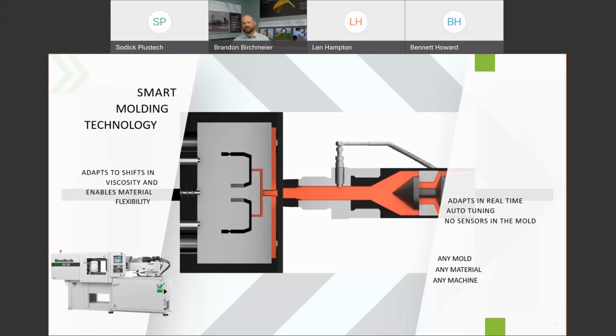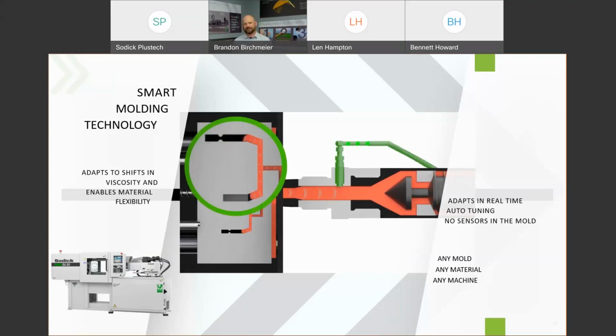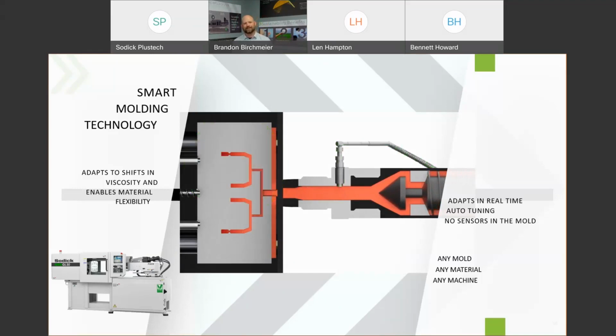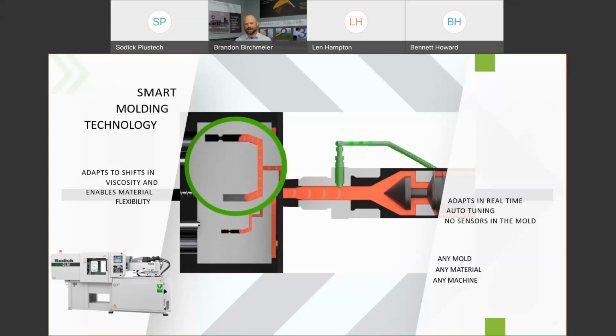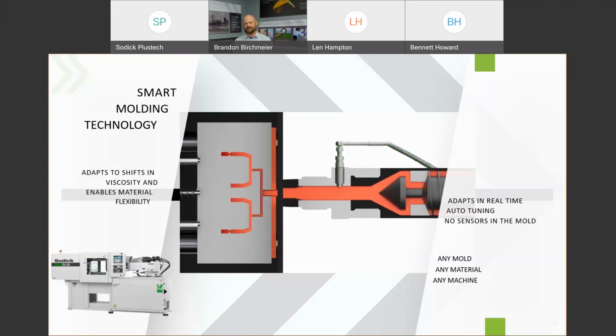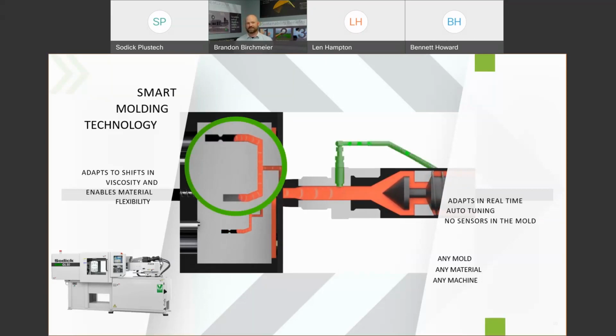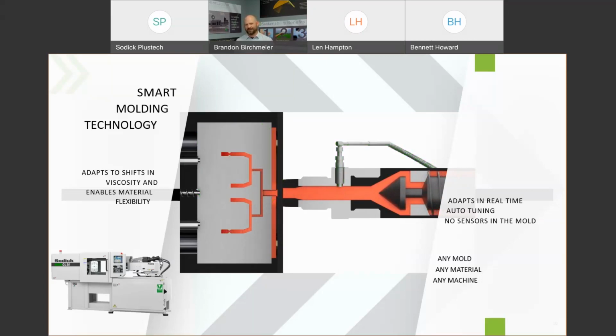This next cool animation is just showing how geometry is dictating velocity. And here's a great example. Being a wholly owned subsidiary of Procter & Gamble, we have lots of living hinges, as you can imagine. This is kind of showing how a living hinge would impact the process, right? Traditionally, if I was just molding, you would need to do a short shot series, maybe even install sensors, to understand where the flow front is before or after that hinge, that thinned out section. Maybe you do want to slow down or do something in your process to compensate. Again, with the iMFLUX process, as I see those areas of more resistance or less resistance, I will make up for that in velocity. So once I see that choke point, my process will actually slow down a little bit through the living hinge, and then speed back up to finish.